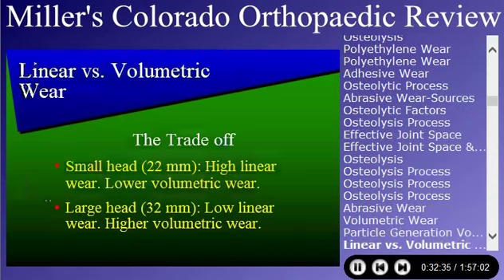You could use the small standard Charnley head, which is 22 millimeters, and what you're going to see there is higher stresses at the head interface, so you're going to have a high linear wear, but it's low volumetric wear, and it's not going to generate a lot of debris, and you're not going to have a lot of osteolysis. The problem is that over time that's going to wear through and wear out. On the other hand, if you use a large 32 millimeter head, you have a big ball, large volumetric wear, and you're going to fail by osteolysis. The polyethylene is not going to wear out, but you're sure going to get a lot of osteolysis.